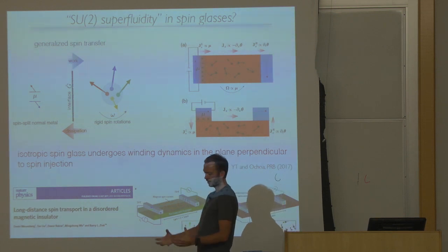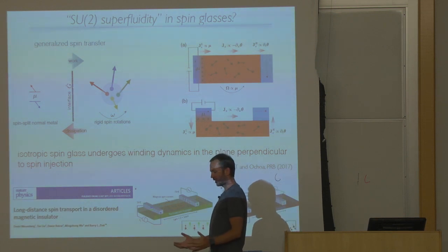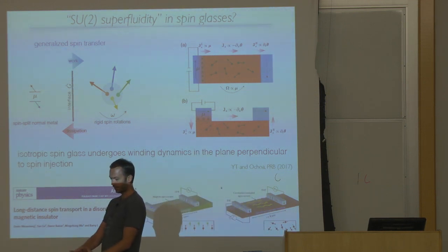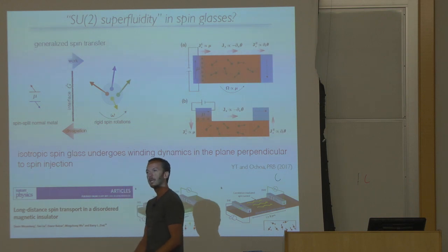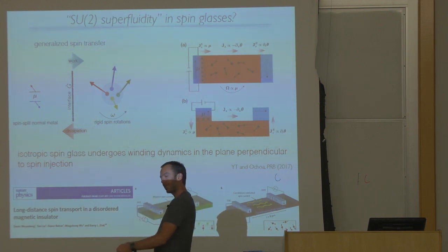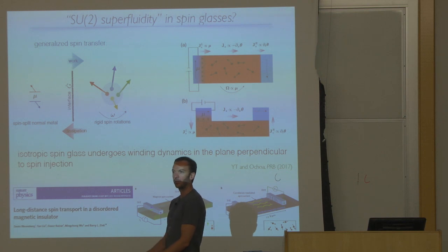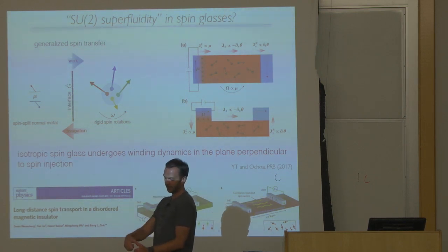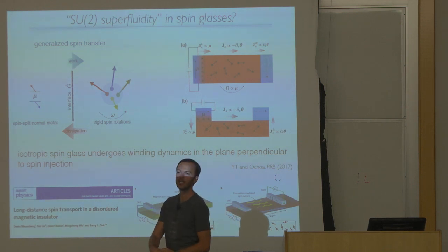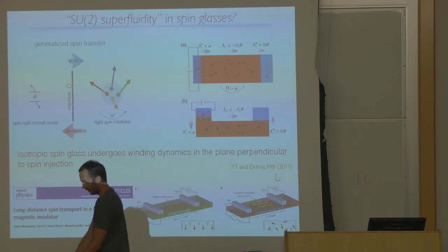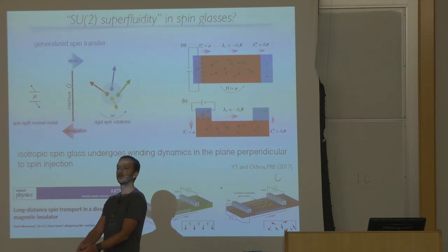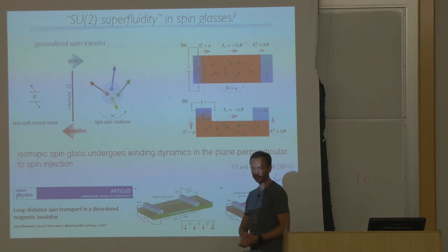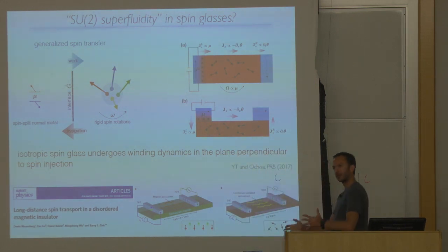For skyrmions, they would seem more robust, because so long as the skyrmionic texture is continuous, there's no way to unwind them. To unwind skyrmions, you have to go down to the atomistic scale. So the energy that protects skyrmions is determined simply by the atomistic exchange. But of course, there could be some spots with an impurity where the atomistic exchange is reduced. So the details of this process could be very complicated in different regimes.